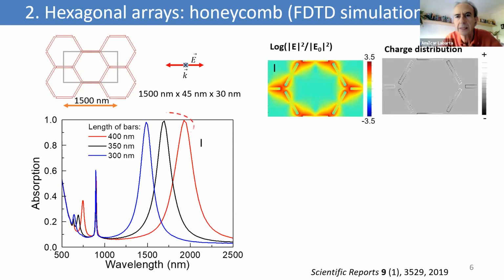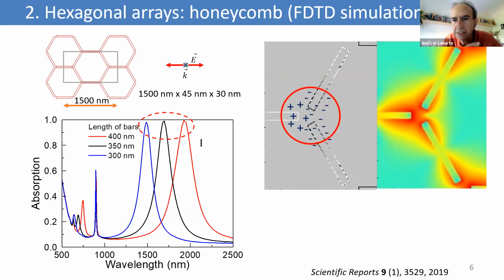Here, there is the distribution of the modulus of the electric field and the charge distribution corresponding to the first peak. And if we zoom these images, you can see that the charge distribution in the 3 bars that are converging at a vertex is not exactly what we can expect for a simple dipolar excitation, because we have 2 bars with a negative charge and only a single bar with positive charge. This is something similar